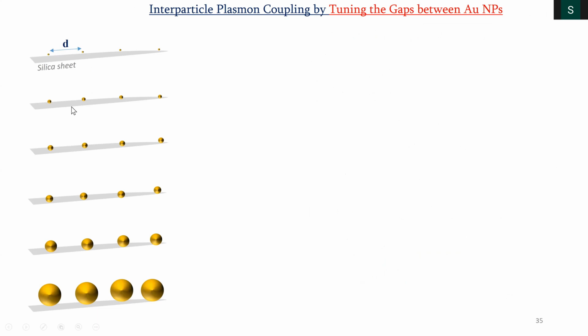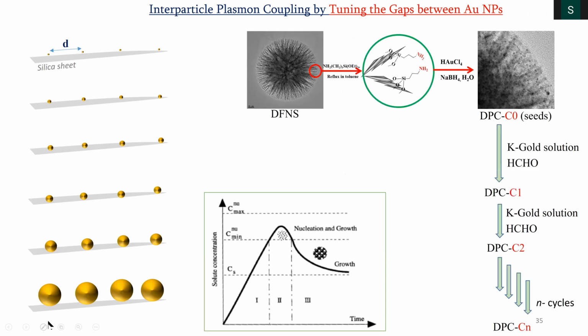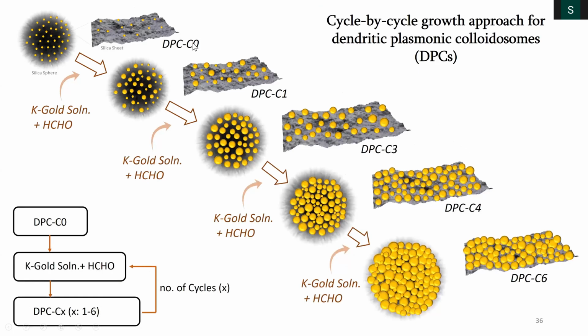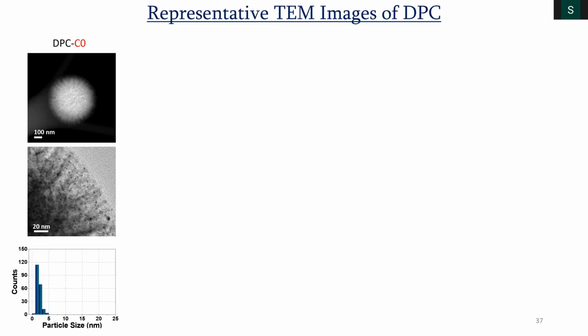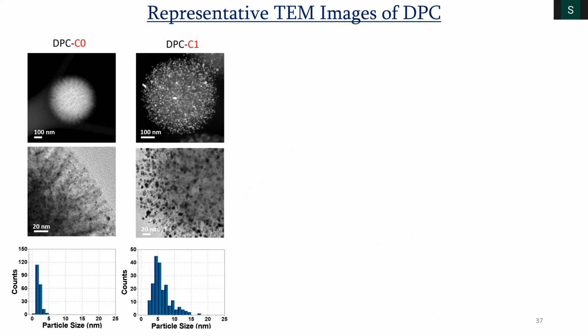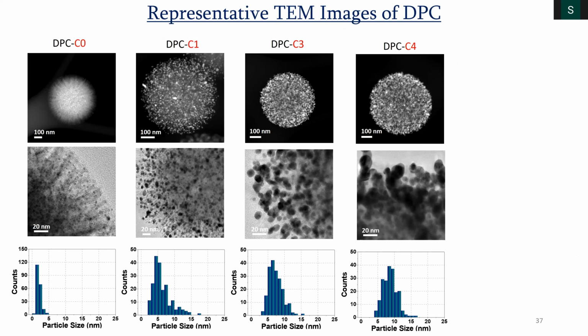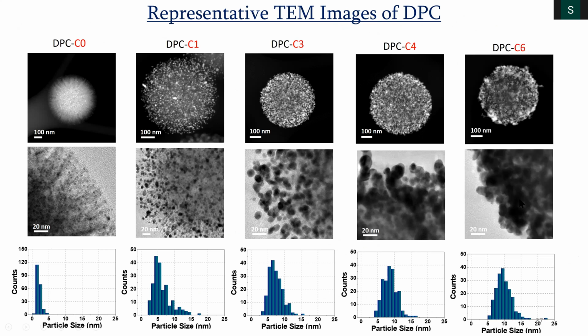We tuned the distances between the gold particles, D. You can see D is decreasing by a cycle by cycle approach, where C0, C1, C3, C4, C6, you see the gold particles are coming together, and also there is a heterogeneity in the particle size. These are the TEM images indicating that when I go from one cycle to another cycle, particles are coming closer to each other. Even in C6, they started connecting. Even in C4, some portions are connected.